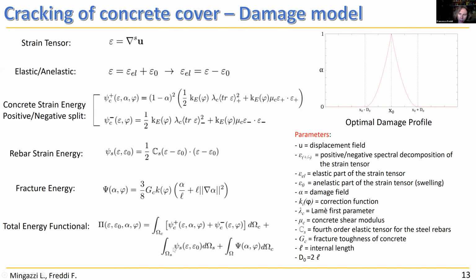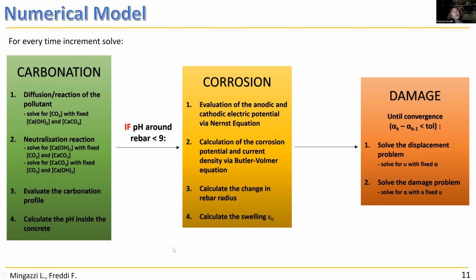So I think that I've spoken a lot and I've said a lot of things, so it's better to sum up everything. So for each time, I'm solving these three problems. The carbonation. First of all, I'm solving the diffusion reaction equation in order to determine the concentration of CO2 within the concrete element. After that, I evaluate the concentration of calcium hydroxide and calcium carbonate, evaluate the carbonation profile, and determine the pH within the concrete. If this is greater than 9, corrosion is not starting, so I go on with the carbonation process. Otherwise, if the pH has been reduced a lot from the carbonation reaction, corrosion starts.